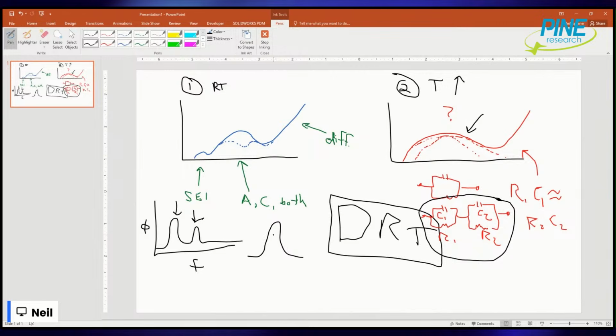Now, all that being said, another possibility for why you get fewer semicircles at higher temperature is because your battery is starting to fall apart. One of the things that can happen at high temperatures is the SEI can decompose or fall apart. It depends on exactly how high a temperature, and on the battery. It's not a guarantee. But if the SEI were to collapse, this semicircle might disappear. It might get absorbed. There won't be any more resistance or capacitance through an SEI layer on either your anode or your cathode. So that could be a bad sign at higher temperature.